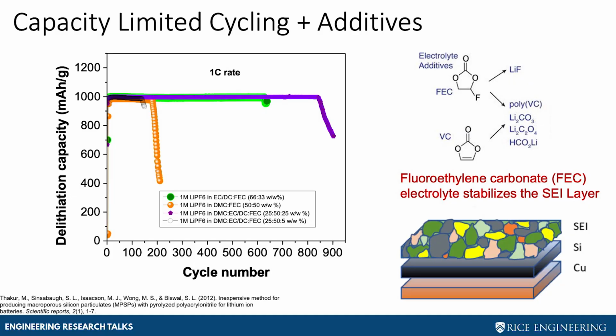So what we decided to do was add some new types of additives to our electrolyte. The one that we chose was a fluorinated electrolyte, fluoroethylene carbonate. What we found was that it's able to stabilize that solid electrolyte interface. And once we added this FEC into our electrolyte additive mix, we went from, say, 300 cycles to now being able to go up to 800, and even some of them are now up to 1,000 cycles.